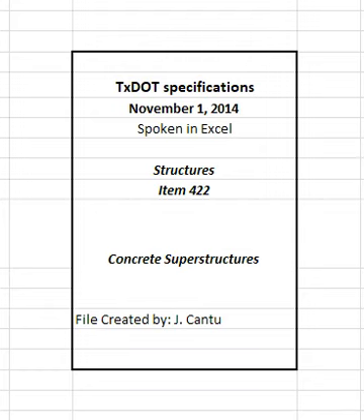Work the screeded surface to a smooth finish with a long-handled wood or metal float or hand-floated from work bridges over the slab. Floating may not be necessary if the pan float attached to a transverse screed produces an acceptable finish. Avoid overworking the surface of the concrete. Avoid use of finish water. Perform sufficient checks, witnessed by the engineer, with a long-handled 10 feet straight edge on the plastic concrete to ensure the final surface will be within specified tolerances.